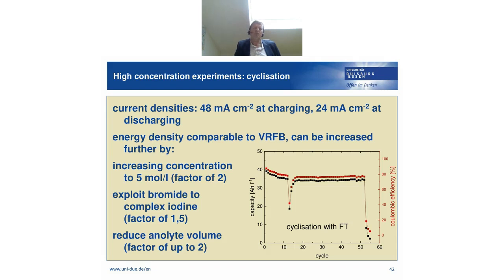We did some cycle experiments, charge-discharge cycles with a high concentration. And as you can see here, again, we could obtain more than 50 cycles, but the coulombic efficiency is lower than compared to the experiments with a lower concentration. So there's still really some room for improvement. As I've pointed out before, we can still, in principle, increase the concentration up to 5 moles per liter. We can exploit bromide to complex iodine and reduce the anolyte volume to achieve higher energy densities.